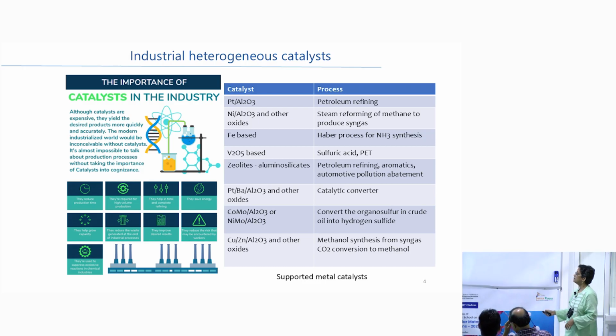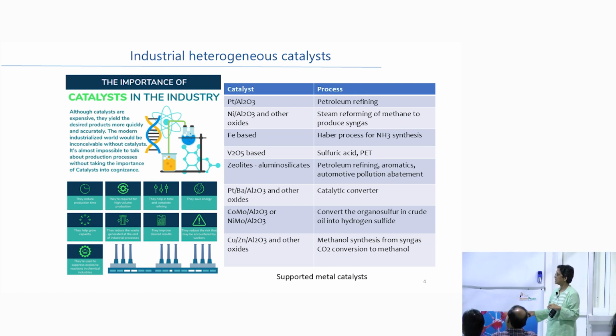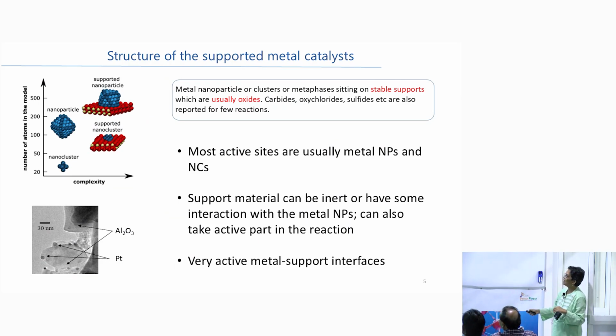And then another thing is methanol synthesis. Again, large scale, like 10,000 tons per day is an average production of a plant. But if you look at all these things, when I write platinum/alumina or nickel/alumina, it means that platinum particles are deposited on the oxide. And in general we call these types of materials supported metal catalysts. So this is nothing but nanoparticles of the active metal, nanoparticles and nanoclusters, like I said, sub-nanometer to 25 nanometer, which can be used as catalyst, deployed on supports.